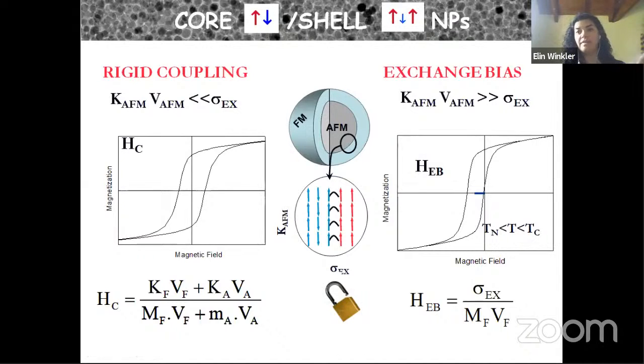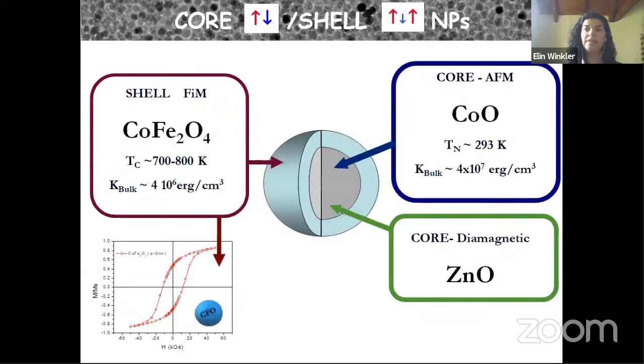So with all these ideas in mind, we're going to fabricate our systems. Well, our first challenge is we want to increase the magnetic anisotropy of the system. We want to fabricate a hard magnetic material, for example, to fabricate a new magnet. In that case, we choose a ferromagnetic material, cobalt ferrite, that itself has a very large anisotropy, and we combine this cobalt ferrite with cobalt monoxide. The cobalt monoxide is an antiferromagnetic material that has an order of magnitude larger magnetic anisotropy. So in this case, we synthesize nanoparticles of cobalt monoxide, and then we overgrow the cobalt ferrite over the cobalt monoxide.